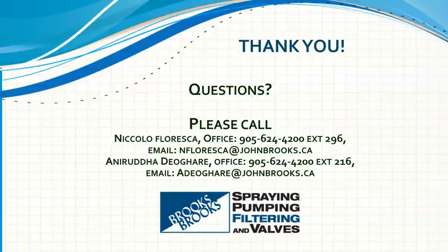Thank you. Nico and Annie, would you like to add anything? Or actually, these were our last questions. Yeah, so our Compress software provides that when the governing thickness is more than 1.5 inch for the shell, it gives the requirement of post-weld heat treatment. And the Compress software itself totally follows the ASME Section VIII Division 1 or Division 2 code. So once the thickness exceeds this governing thickness, it automatically indicates that post-weld heat treatment is required for this particular vessel.